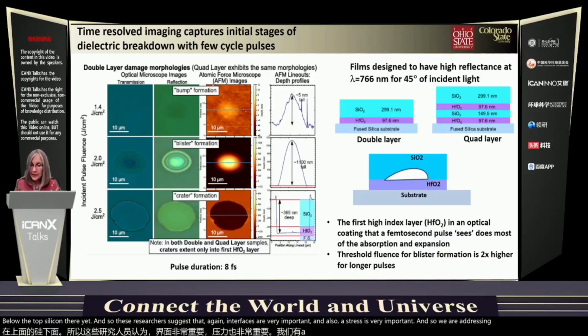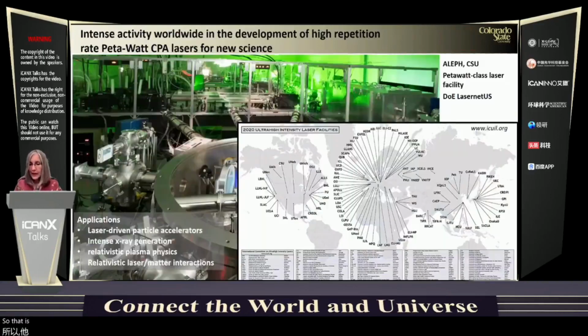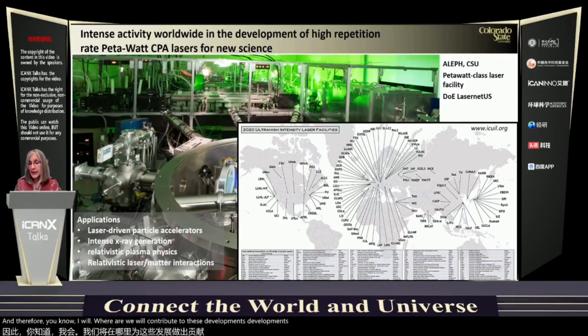And so we are addressing those issues by modifying the materials. There is intense activity worldwide in developing multi-terawatt and petawatt lasers. Therefore, our work will contribute to these developments by enabling much higher energy extraction out of the solid state amplifiers, through the improvement in the laser damage performance of the coatings. Furthermore, if we make more robust coatings, the size of these lasers could also be reduced.